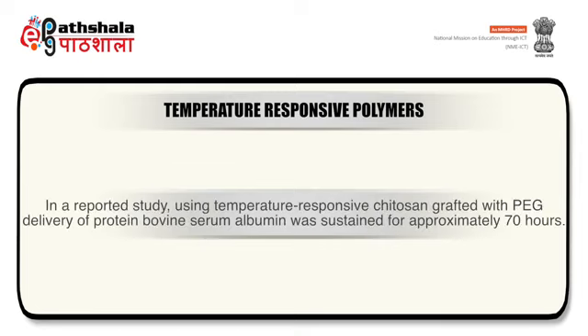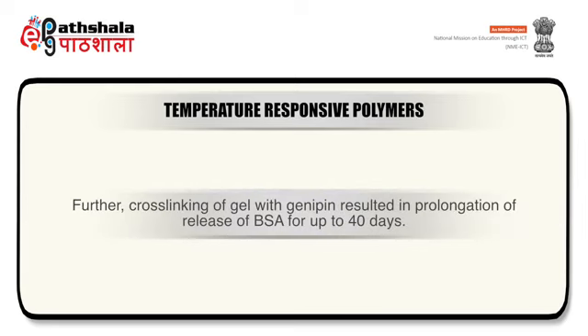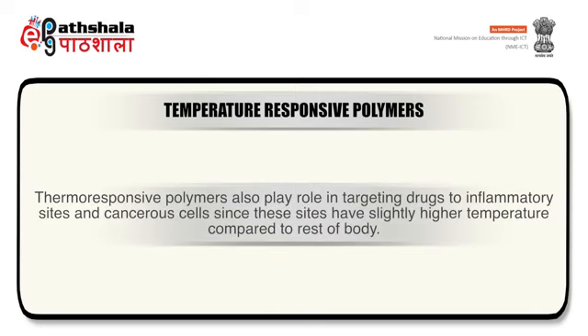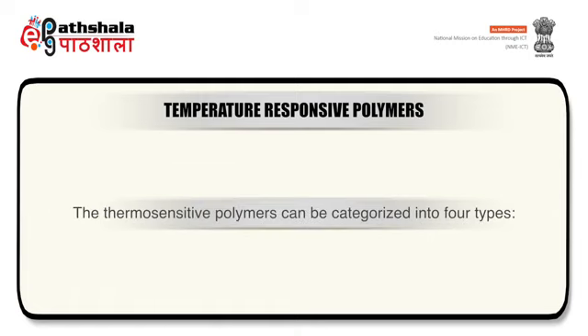In a reported study using temperature responsive chitosan grafted with PEG, delivery of protein bovine serum albumin was sustained for approximately 70 hours. Further, cross-linking of gel with genipin results in prolongation of release of bovine serum albumin for up to 40 days. Thermoresponsive polymers also play a role in targeting drugs to inflammatory sites and cancerous cells since these sites have slightly higher temperature compared to rest of body. The thermosensitive polymers can be categorized into 4 types.